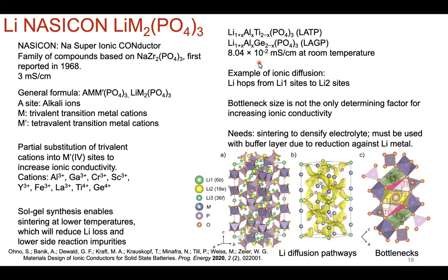Okay. And the other thing is, of course, we've talked about the intrinsic ionic conductivity properties. The two other pieces to balance out, the materials design and whether or not these materials can be realizable commercially, is, of course, when you put it against lithium metal, and also in processing the materials, often you really have to process these powders. You can't just press a pellet, or you can't just deposit down these materials. You really have to either densify or sinter under conditions that make it difficult to scale up and manufacture. So fundamentally, they are really interesting materials, and there's a lot of promise, but the second step is a difficult step. Okay.